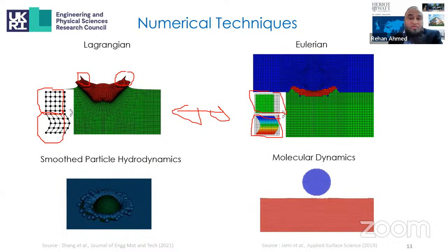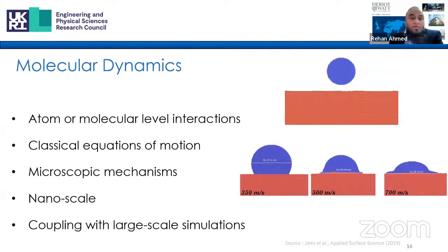Molecular dynamics is generally used in small-scale deformations, and molecular dynamic simulations can capture the interaction of atoms or molecules using the classical equations of motion. Now, grain boundaries, structural transformations, friction, and shock waves are some of the fields where molecular dynamics has been applied. And this slide shows the particle interaction of a 21.4 nanometer diameter particle of titanium at 3 different velocities of 350, 500, and 700 meters per second.